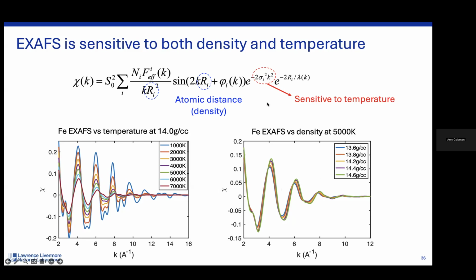But it's also sensitive to temperature, by means of the mean square relative displacement - that's this sigma squared term up here. Practically what this looks like in XAFS data is a reduction in the amplitude of these oscillations as you're moving to higher temperature.